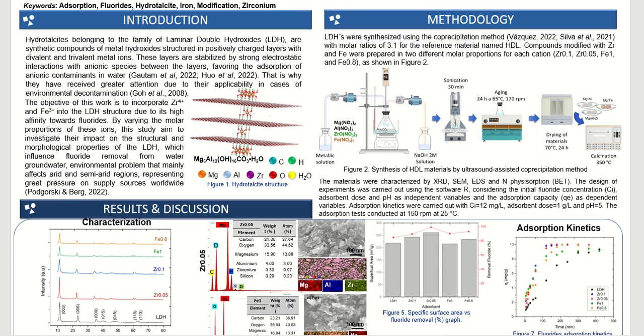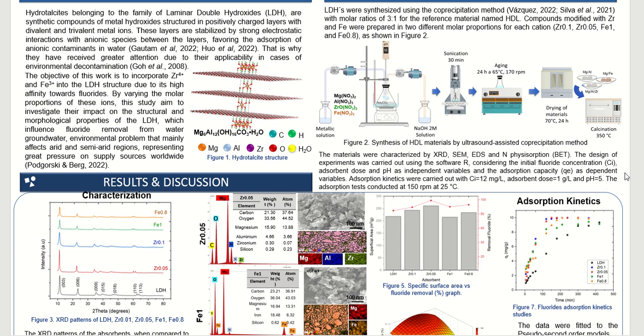Methodology. This section consisted of synthesizing by the co-precipitation method, which is a gradual addition of a metal solution and an alkaline solution and then subjecting the mixture to ultrasonic agitation, followed by aging, and then washing to obtain a neutral pH in order to eliminate soluble compounds. Finally, it is dried and calcined to obtain a white powder, as seen in Figure 2.